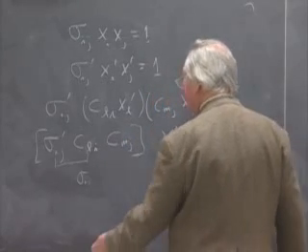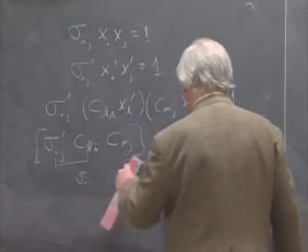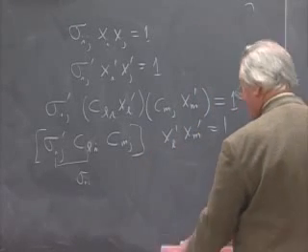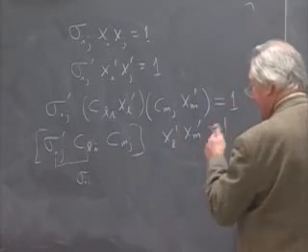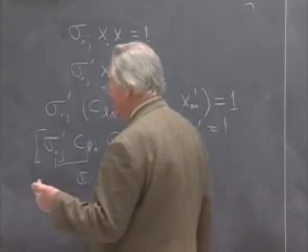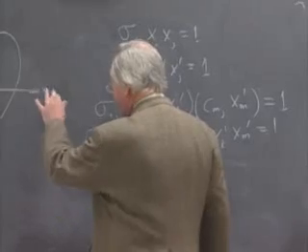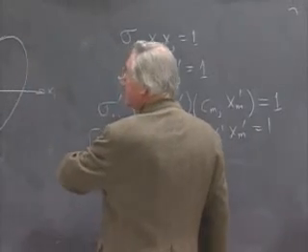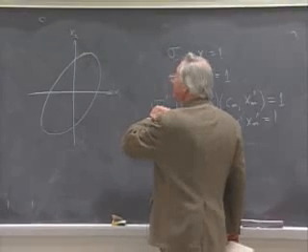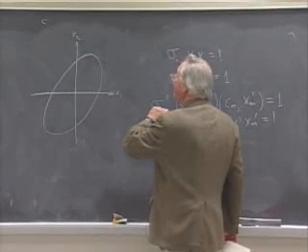So it's the same set of coefficients, and that is a technicality which probably you wouldn't want to worry about. So anyway, the elements of the tensor transform in the same way that the equations for the surfaces transform. So if you change coordinate system, the coefficients that you should use should be the elements that are in the transformed tensor.